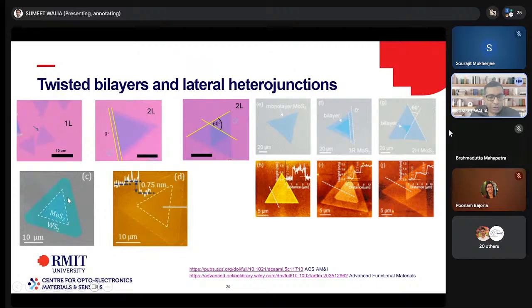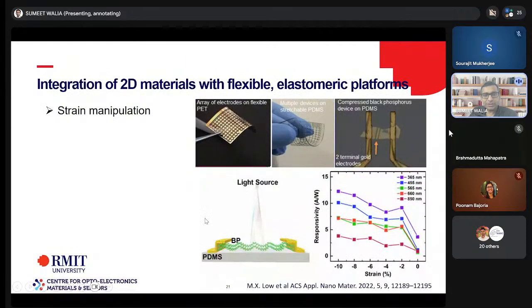We also looked at lateral junctions, so you would have seen a lot of bilayer junctions, vertical junctions of materials. What you see down the bottom left is essentially a planar junction of MoS2 and WS2, and there's an atomically sharp boundary at that junction that creates a built-in electric field that we can utilize to trap charges and create different types of phenomena. So again, I've listed both the papers down the bottom. If you're interested, I'll be happy to share the slide deck with you later as well if it helps.